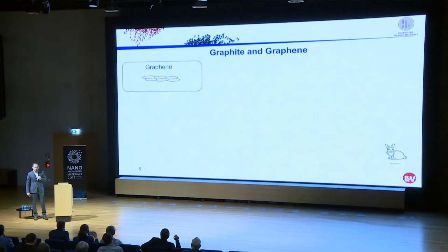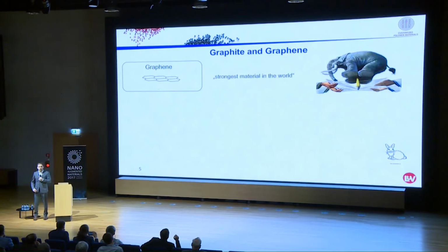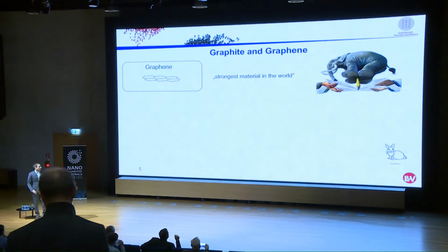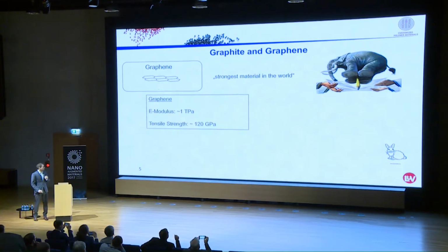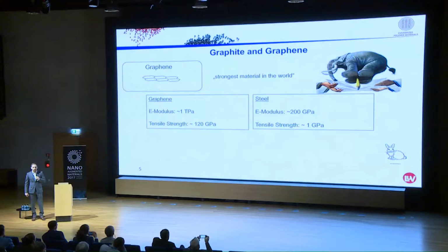So nowadays we find that it's kind of a gold rush for graphene, because graphene is supposed to be the strongest material in the world. Professor Hone from Columbia University said it would take an elephant balancing on a pencil to break through a Saran wrap of graphene. What does it mean in numbers? Graphene has an E modulus of about 1 terapascal and a tensile strength of about 120 gigapascal. So it outperforms construction steel about 100 times.